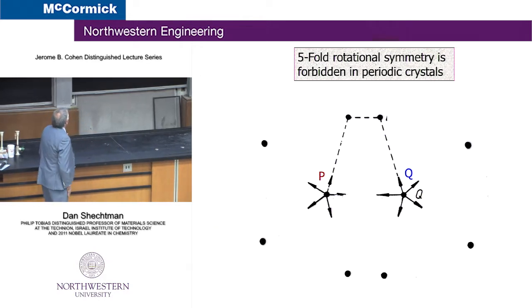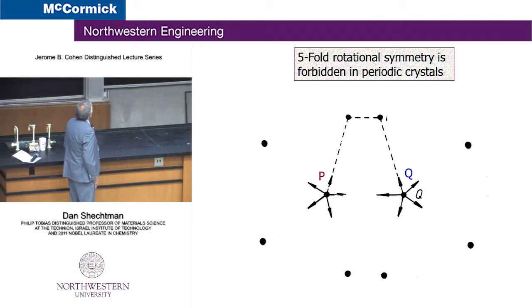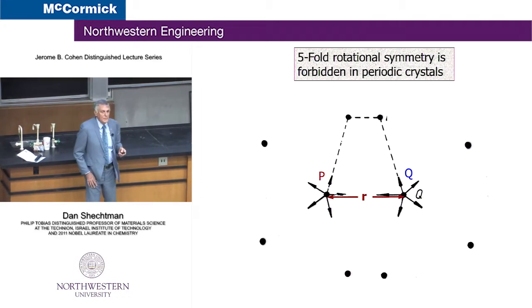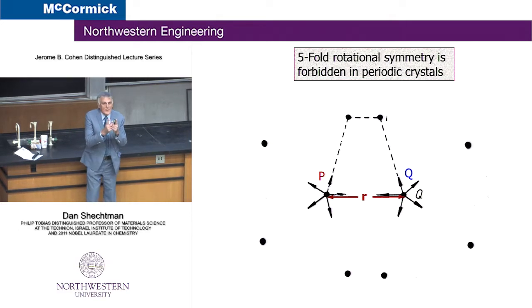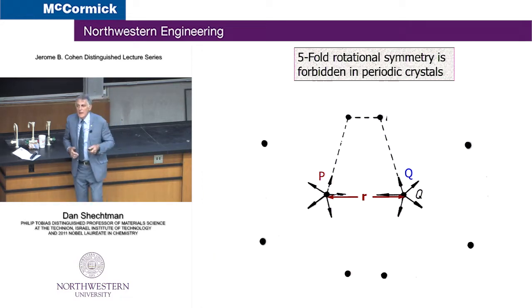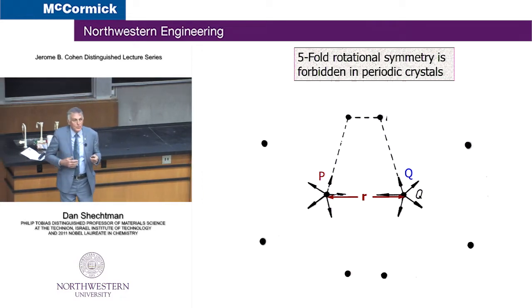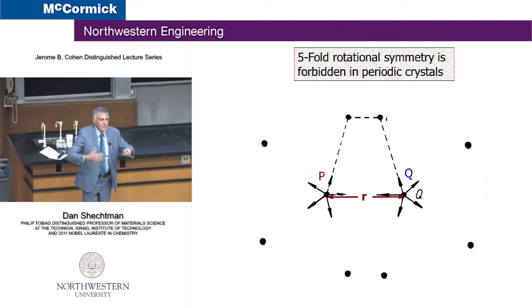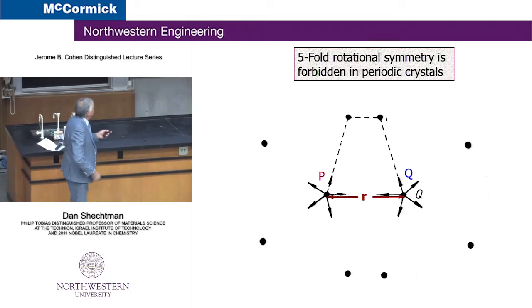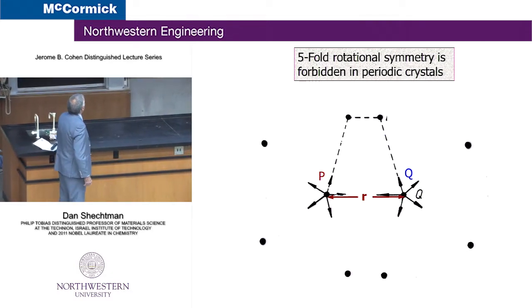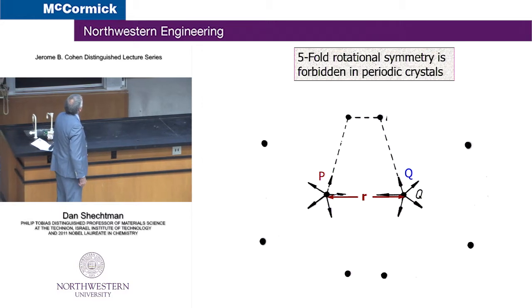So here goes. Take 2 atoms, P and Q, and choose them in such a way that the distance r between them is the minimum distance in that particular crystal. Okay, so the r is the minimum distance between 2 atoms. Now, if 5-fold rotation symmetry is allowed, is possible, then you can rotate Q around P 5 times and P around Q 5 times. Let's see what happens when you do that.